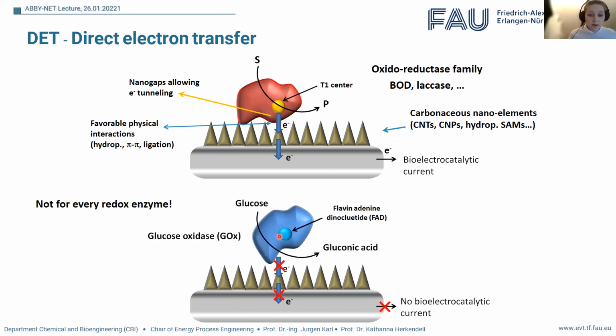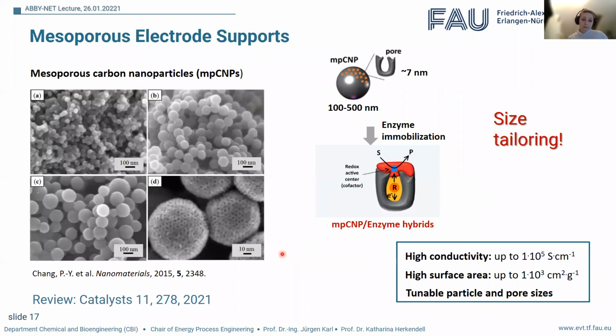This is mostly true also for the larger oxidation enzymes that we commonly use, for example, for the abundant source in most medical-related systems, like glucose, which you can even find in your blood, and which is usually catalyzed by the enzyme glucose oxidase. It is so insulating that no matter which stacking material you put underneath, it would not make the active center, flavin adenine dinucleotide, or FAD, communicate with the surface. For this, you need to develop other mechanisms. There have been many publications in the past to find techniques to make this more efficient and to somehow enable electrical communication. What we developed is a very straightforward and cheap method to electrically wire, for example, glucose oxidase to the electrode surface, and this is based on mesoporous carbon nanoparticles.